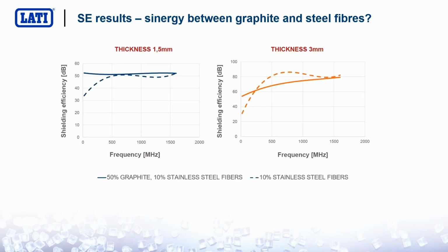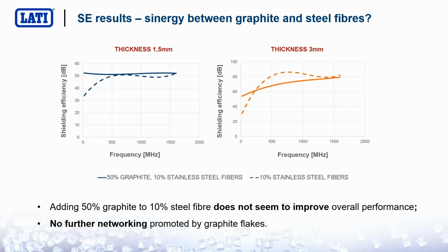We also wanted to test the same experiment. What happens by mixing graphite and steel fibers? Actually, there was no improvement. By mixing also a huge quantity of graphite to steel fibers, we saw no benefits in the shielding efficiency. Maybe we were not able to create a properly developed networking of graphite particles. Maybe we should change the type of graphite or change the shape or increase the content, but we didn't see this synergy between graphite and steel fibers.